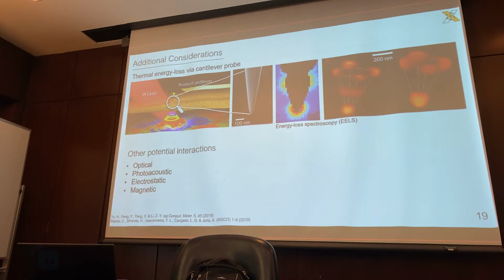And one group, and this is something that I showed in a previous presentation, but for a different purpose, looked at the energy loss, used energy loss spectroscopy to look at the plasmonic effect at the tip itself. And they modeled this. So they found the different areas where you might actually be losing thermal energy during the process. So if we can somehow insulate this process, we can increase the efficiency of our signal detection of our material expansion.